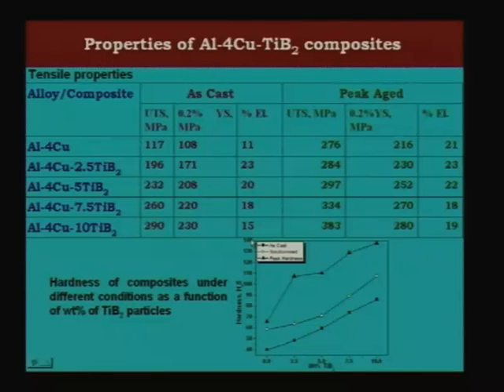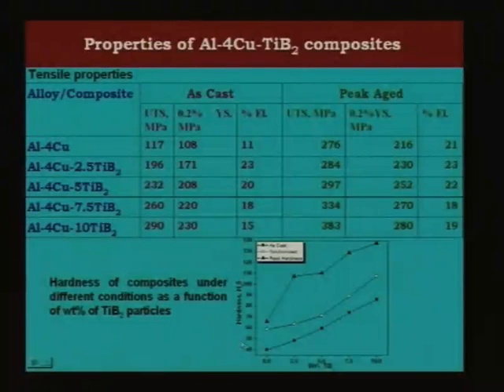But what is important to see is that the elongation is good enough to give you a dimpled fracture, which is what is important for any structural component. Any material which you want to use for structural applications has to have a certain amount of ductility. If it does not have, you cannot use it for any structural application. This is very important. And you can see here the hardness which is plotted in the as cast condition, the solutionized condition and the peak age condition. It increases with increasing volume fraction. This is expected, as we know that higher and higher amount of TiB2 will give you higher strengthening.